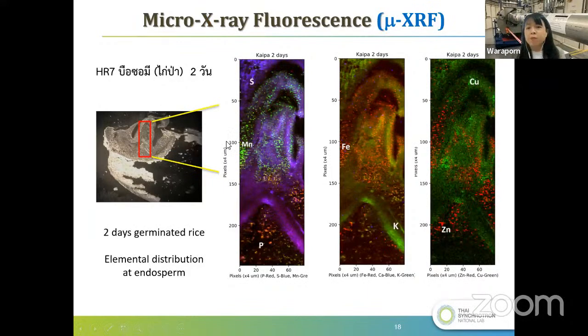This one is an example of XRF measuring elemental distribution at the endosperm of 2-day germinated rice. You can see that the rice sprout is coming, so we can see the localization or co-localization of each element in each part of the endosperm, like iron, the red one. The iron distribution is in here, but manganese is also quite close to the position of iron, and the copper is in here, totally different as well.